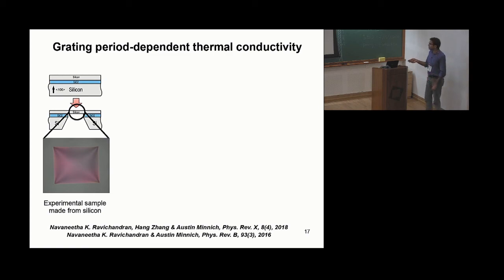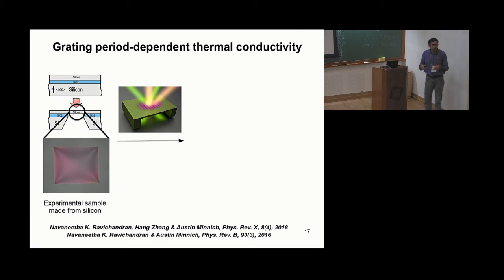For that, we basically grew thin film samples, such as the one shown here, which is just a silicon membrane, and used this transient grating experiment to get length-dependent thermal conductivity measurements.